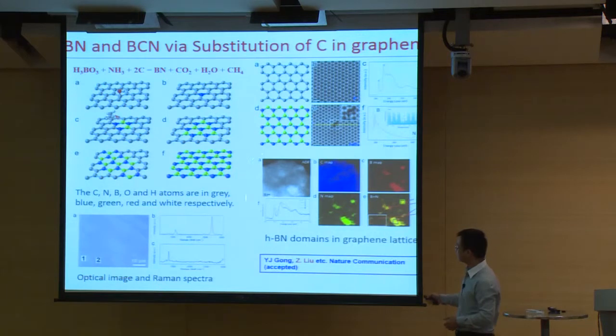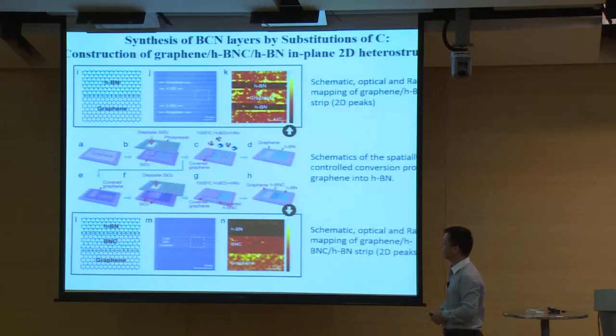And for the partially converted BCN sample, in the microscope we can see some nanodomains, boron nitride nanodomains embedded into the graphene lattice. About what temperature? 1,000 degrees.